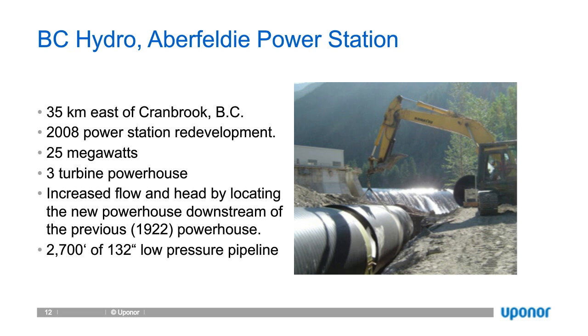And that's really because the width of the profile that's used to make the pipe gets wider and wider. So we get slightly lower Manning's N and Hazen-Williams C factors as the pipe size increased, but the absolute roughness is fairly consistent regardless of size. And for very large pipe used in hydropower stations, the absolute roughness is the value that's typically used in the hydraulic calculations that are done for the project.